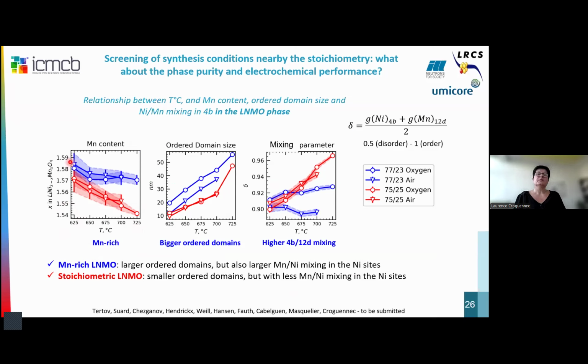Look here: in blue, we have the manganese-rich materials versus the red here, the stoichiometric composition materials. You can see that in these materials, we have bigger ordered domains when we are manganese-rich, versus, for the same temperatures, smaller domains at the stoichiometric compositions. And you can also see that we have a higher mixing here between the nickel and the manganese sites.